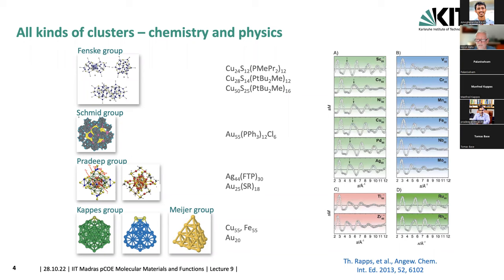And this is taken out from one of Manfred and co-workers' papers. These are pair distribution functions of the different clusters of the different elements at negative charge here. So this would be scandium 55, negative charge, cobalt, nickel, and so on. And what the group has done was to measure the electron diffraction pattern to get an idea of the structure of these clusters, which were trapped in the vacuum in a so-called Paul trap. And then with the help of a comparison with DFT calculations, you can determine the structure.